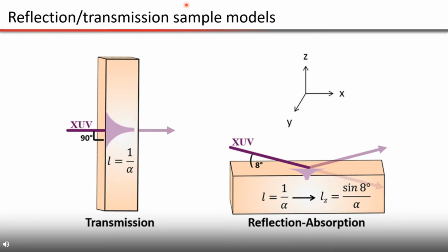The line shapes of transmission versus reflection spectroscopy will turn out different in your final spectrum that you collect, but conveniently, this is relatively trivial to compromise, because there are these developed mathematical relationships, the Kramers-Kronig equations, which allow you to basically extract the same resonance information from either setup.